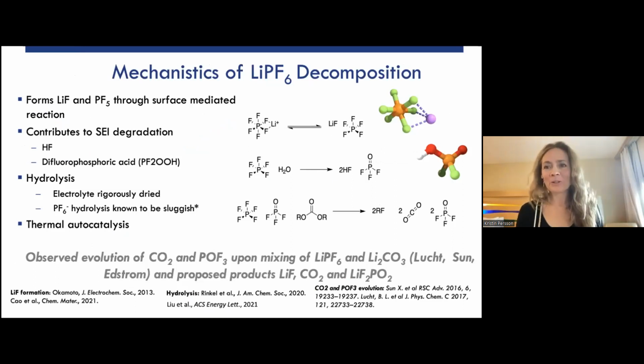Okay, so you might wonder, what on earth about the salt? I've only talked about solvents. The SEI is highly dependent on the decomposition of the salt. And this has caused modelers quite some headache in the past because we have been unable to find the mechanistic decomposition path for LiPF6, which is our majority salt in lithium ion battery chemistry. We know that it forms lithium fluoride. We believe that PF6 basically just donates an electron to lithium. So that's through a surface mediated reaction, that's fine. But after that, PF5, we have not been able to figure out how it decomposes.